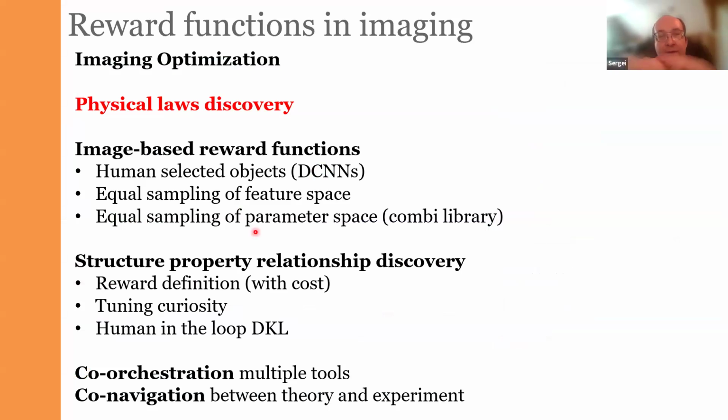So that's one example. And by the way, in atomically resolved imaging, whether it is scanning tunneling microscopy or electron microscopy, optimization of imaging is relatively much easier. The reason is that once you have access to the atomic structure, it's very easy to judge the quality of the image based on the Fourier transform. All we have to do is look at the position of the peak in the Fourier transform, which is visible, and that gives us the information limit of the technique.